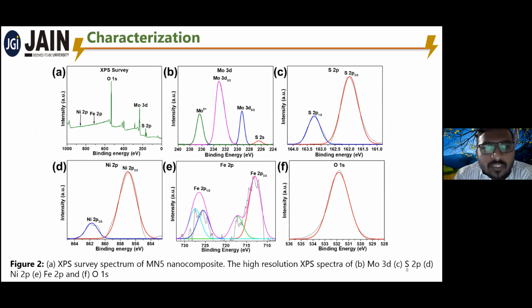In the XPS survey spectrum, we can clearly see that all the metals present in the nanocomposite are present. In the Mo spectrum, molybdenum 3d3/2 and molybdenum 3d5/2 represent that the molybdenum is in the +4 oxidation state, and along with the molybdenum peak, small peaks of sulfur also appear, which represents that bonding takes place between the molybdenum and sulfur.